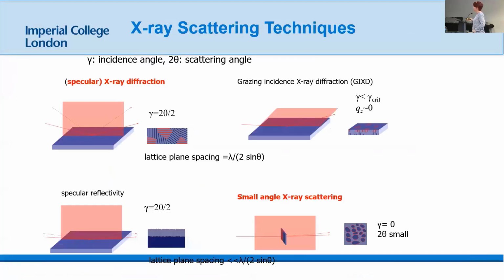If you want to understand strain and morphology and size, then X-ray scattering is the technique you should use. We use two techniques. I've called it specular X-ray diffraction here, that's your normal X-ray diffraction mode, and some small angle scattering. This will give you your lattice parameter, which of course is strain sensitive, and this will give you the size, or the ligament spacing, in the material. And I'm slightly paranoid now that Tony's here because he's the absolute SAXS expert. So no, luckily there are no questions.